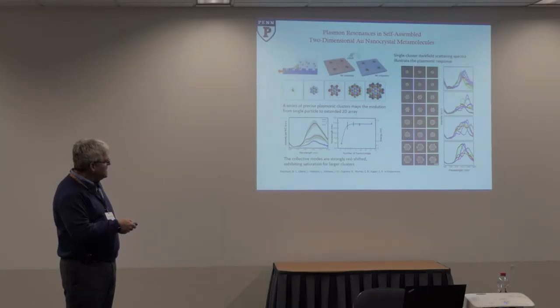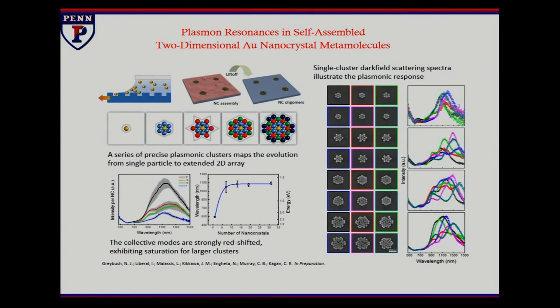But again, the hybridization and the interaction between these systems allow you to look at, and this is across a range in the infrared, so each one of these spectra is the response of an individual cluster. You will see that they're centered on certain positions, but each one is a little different, and that's because, unfortunately, everything matters. You can see that there's a little bit of a defect or a slight difference in spacing. I should have blown this up a little more. Each one of these three, as an example, has a slight difference in the packing density, but the position of that imperfection is different in all three. Otherwise, you would say they're pretty similar in terms of size and shape, but it makes a difference in the fine structure of the different higher order modes in the resonance.